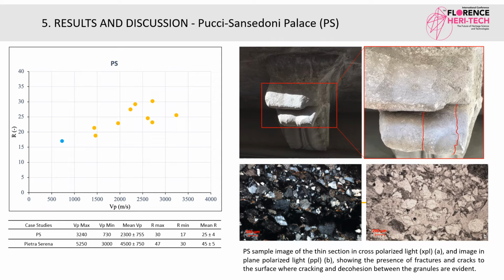From mineropetrographic observations, the stone shows a poor state of conservation, with a low amount of the clayey matrix and microsparitic calcite cement. Several fractures and intergranular porosities are present. The sandstone shows clastic granules of medium size, mainly constituted by quartz, feldspar, fragments of magmatic and metamorphic stones, beside muscovite and biotite in lower amount. The PS corbel shows low values of Vp and R, and in fact in thin section it has high macroporosity and a low content of calcite.